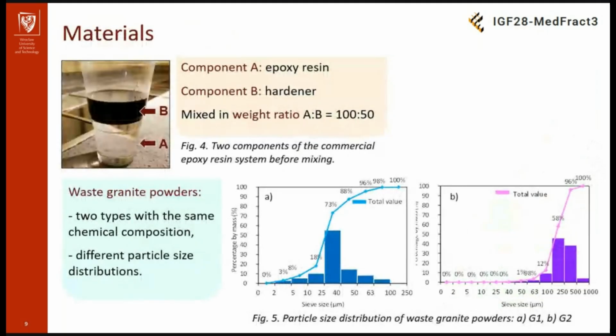In this study, I used a commercial 2-component epoxy resin. Component A was resin and component B was a hardener. They were mixed in a weight ratio of 100 to 50. I used 2 kinds of waste granite powders. Both powders had the same chemical composition, but different particle size distribution. On the figure, you can see the particle size distribution of powder G1 with finer fraction and G2, the larger one.